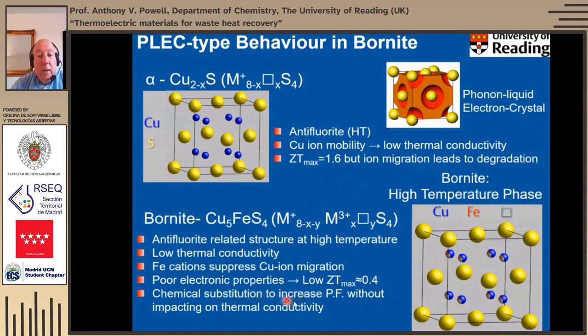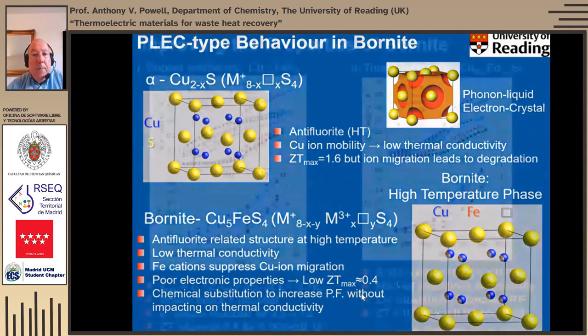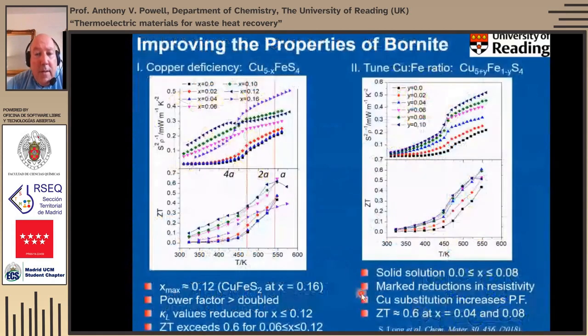So we're going to look at chemical substitution to increase the power factor without impacting on that low thermal conductivity. So I'm going to go through this fairly quickly. We've done 2 different things here. We've used copper deficiency, so we've made some copper vacancies. So again, a similar strategy that has to oxidize some of the remaining copper to maintain charge balance. It introduces some additional holes.